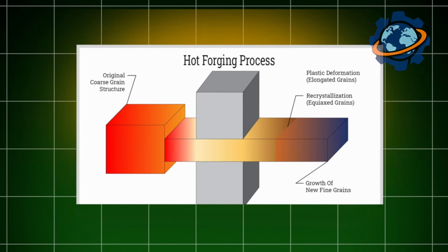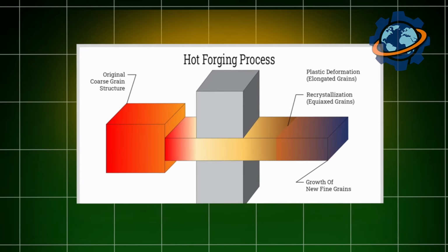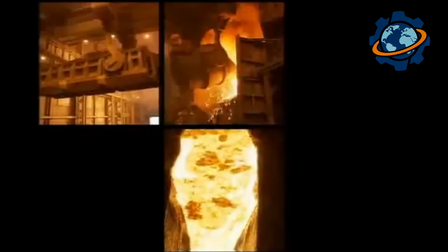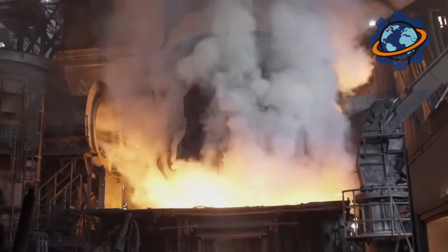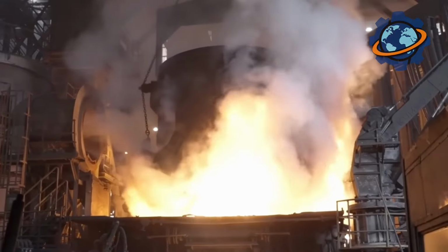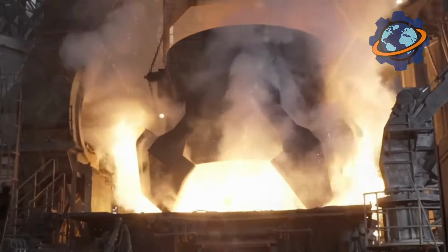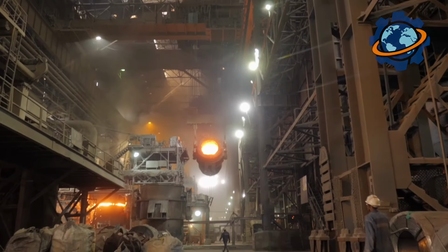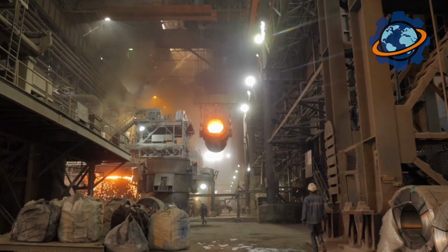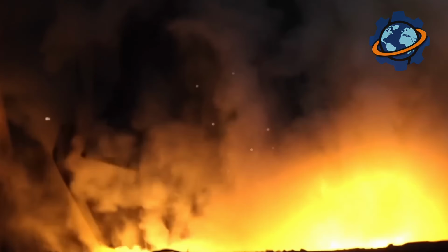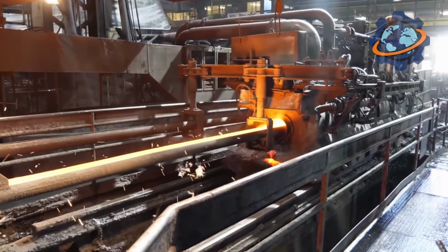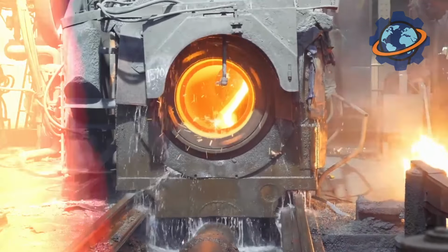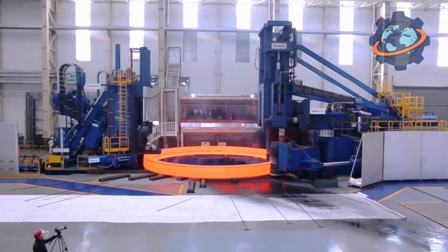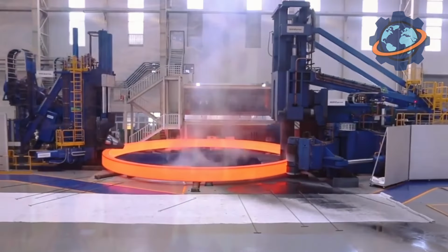Now comes forging, the ancient art of shaping hot metal, scaled to industrial extremes. The 600-ton ingot, reheated to 2,300 degrees Fahrenheit in furnaces large as houses, glows brilliant orange. At these temperatures, steel becomes plastic, not liquid, but deformable under immense pressure. Picture clay that weighs as much as a jumbo jet. Overhead cranes operating at weight limits requiring structural reinforcement throughout the building lift the glowing ingot onto the press bed.